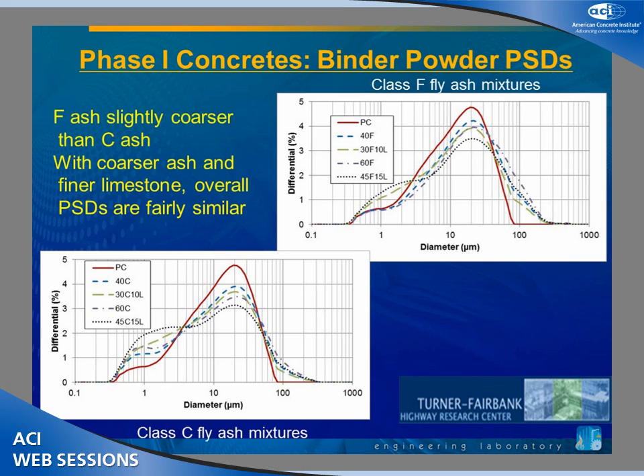We measured the particle size distributions of each of the starting materials, and then we computationally blended those together to get the mixture values. The fly ashes were generally a little bit coarser than the cement. The limestone, of course, is finer. So at the proportions that we're using, you can see that certainly there are differences, if we look at either the F-ash up here or the C-ash down here. But we haven't drastically changed the particle size distributions.